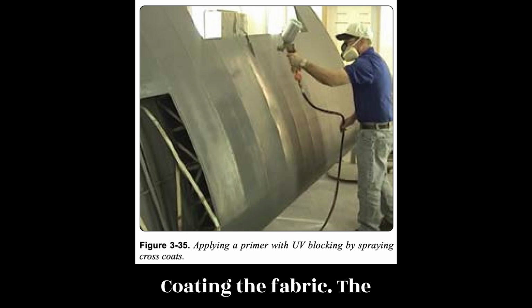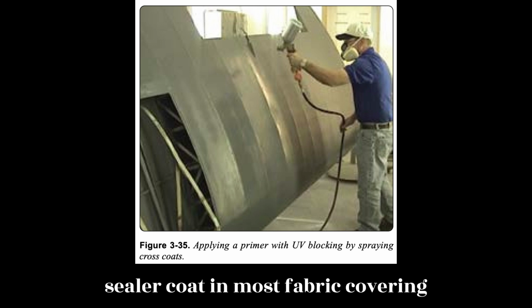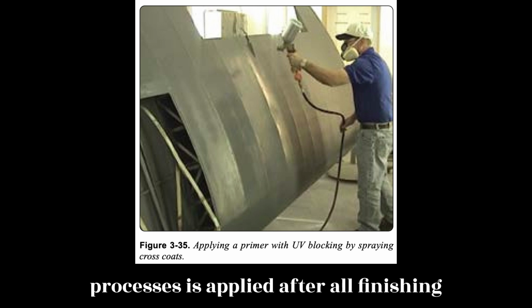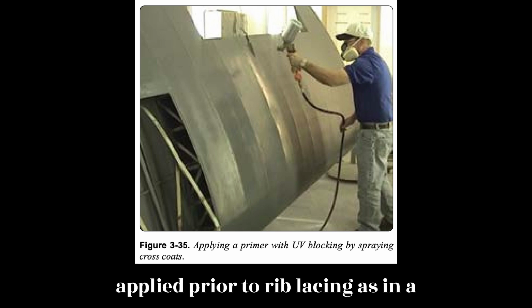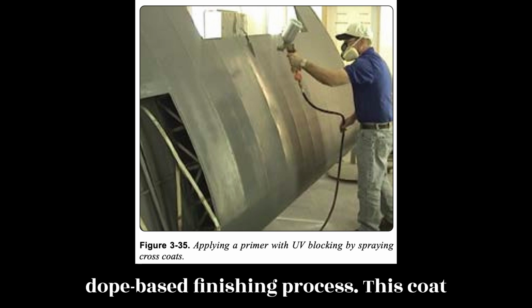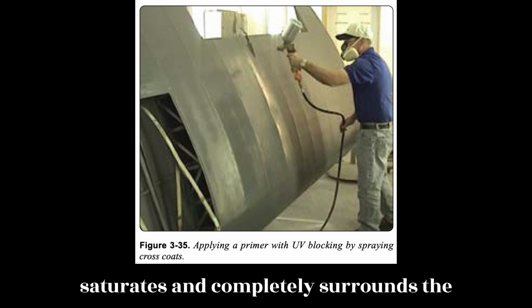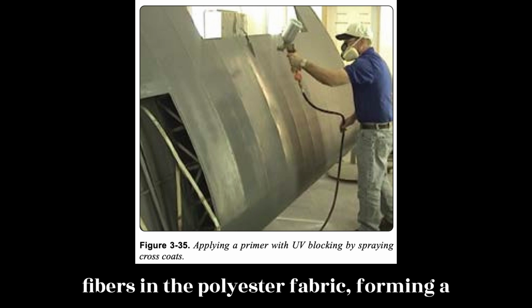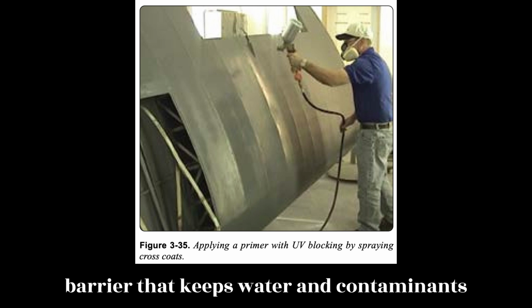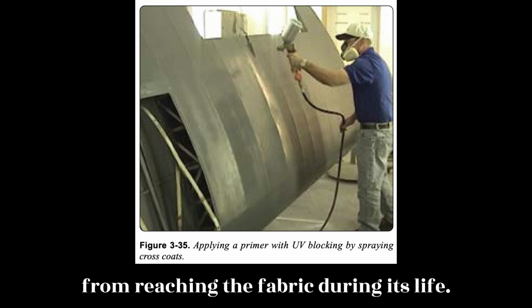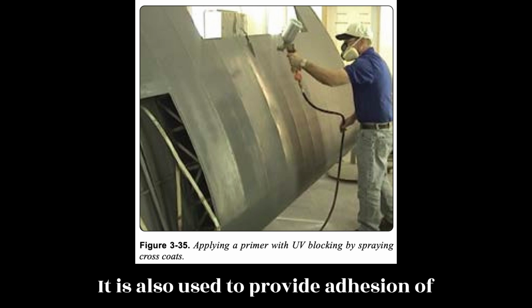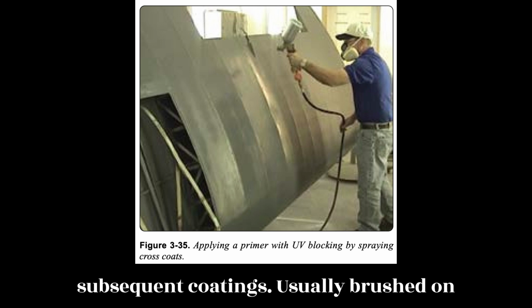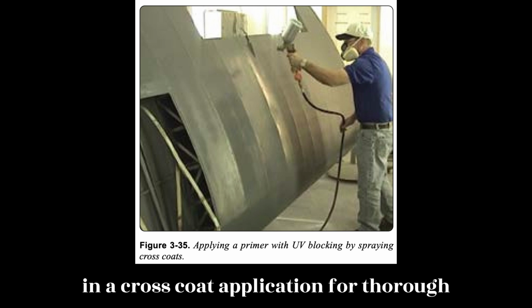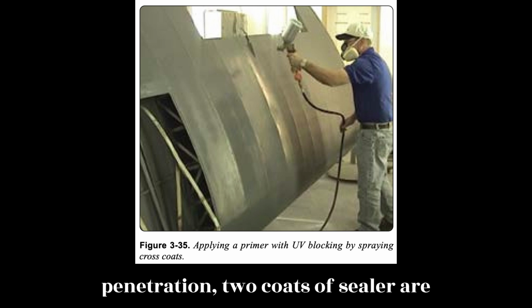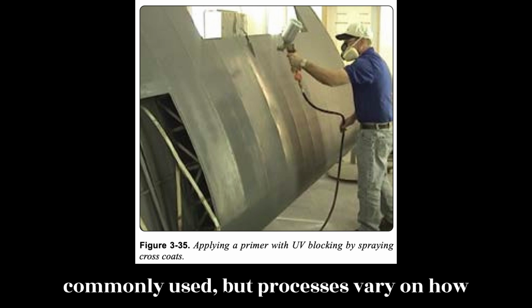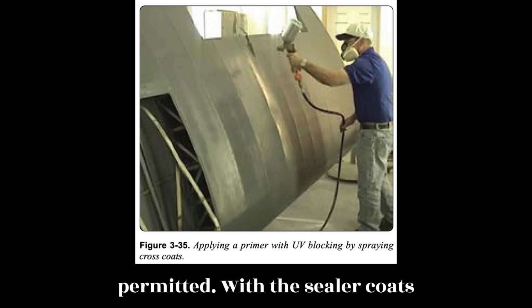Coating the fabric. The sealer coat in most fabric covering processes is applied after all finishing tapes have been installed, unless it was applied prior to rib lacing as in a dope-based finishing process. This coat saturates and completely surrounds the fibers in the polyester fabric, forming a barrier that keeps water and contaminants from reaching the fabric during its life. It is also used to provide adhesion of subsequent coatings. Usually brushed on in a cross-coat application for thorough penetration. 2 coats of sealer are commonly used, but processes vary on how many coats and whether spray coating is permitted.